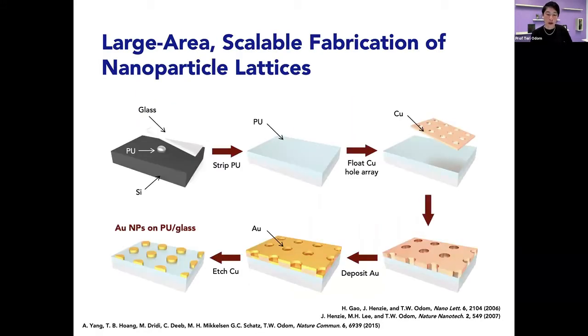So this is a scheme of how we fabricate these particle arrays over large areas. We mostly start off with a floating metal mask, copper or gold. We float it on a substrate that we want to fabricate the particles on. We deposit the material that we want. Then in the case of copper, we can etch it. In the case of gold, we can use Scotch tape to take it off. And in some cases, we can even just use a nitrogen blower to blow it off. So it comes off very, very easily, and then it leaves these particles.